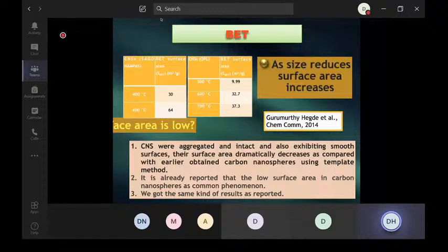That again got some kind of interest. Why is surface area low and specific capacitance high? Because they are all directly connected. If surface area is high, definitely the specific capacitance should be higher. Then we back calculated the surface area using the specific energy data and CV data. Again, surprised, when you back calculate the surface area, it is very high. So that means the material surface area is high, but somehow our BET is not showing that kind of surface area.